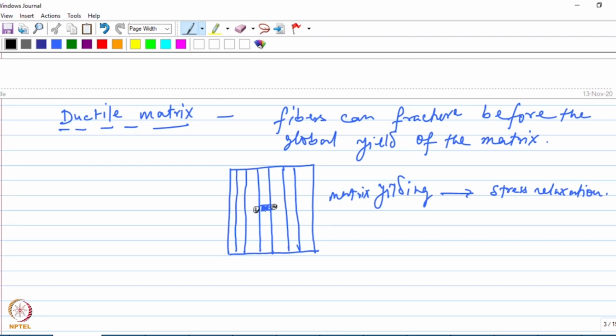And this will prevent the crack from propagating to the adjacent fibers. Okay, so when you have a scenario like this, matrix yielding in a ductile matrix material can have a relaxation effect on the crack, and the crack propagation will be prevented, right? So this is one scenario where the matrix is soft and ductile, right?